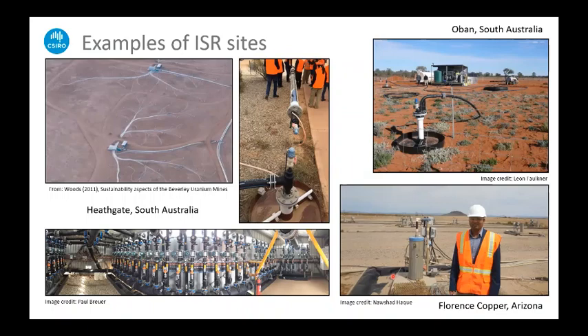This is a colleague of mine, Nawshad. He is standing at the Florence Copper well field in Arizona. So Arizona has a copper porphyry deposit belt, and there are a number of potential ISR operations. The Gunnison copper operation exists there, and Florence copper operation exists too. And they're making good progress in establishing the technique for copper oxide material. So in the copper porphyry deposits, there's usually an oxide layer at the top and the sulfide material at the bottom. The oxide layer is often very fractured and has readily accessible copper that's also readily and easily leachable simply with acid. So a lot of these operations are targeting the oxide minerals as an easy win.